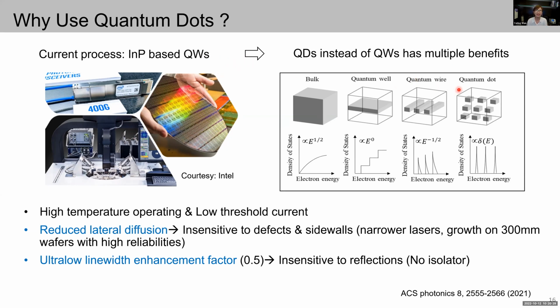Due to the three-dimensional confinement of carriers, quantum dots can promise a lot of performance advantages over their quantum well counterparts, including high temperature tolerance that allows for robust CSWaP operation up to 220 degrees C, the low threshold currents that are capable of supporting low energy consumption, and the reduced lateral diffusion that can reduce the sensitivity to defects and also sidewalls. The former can enable scaling of laser cavities to smaller devices for high density integration, and the latter can enable growth on 300 millimeter silicon wafers with very high reliability.